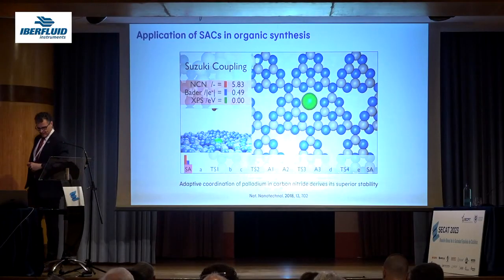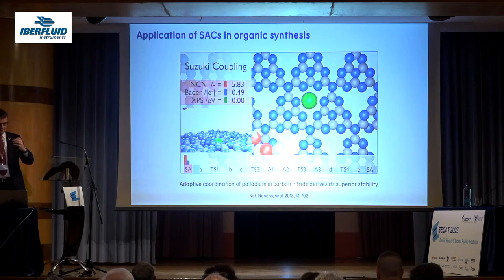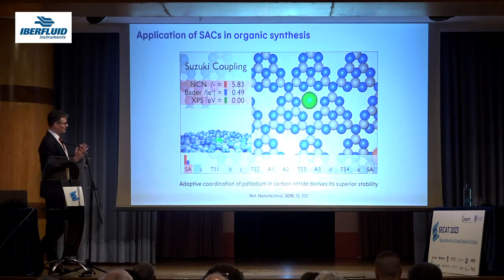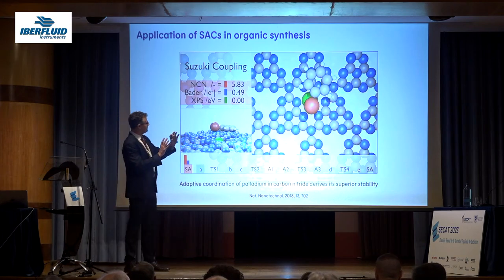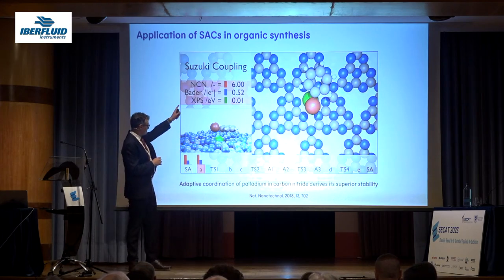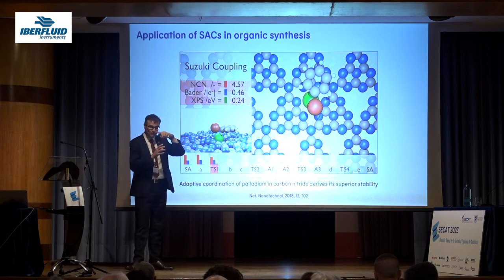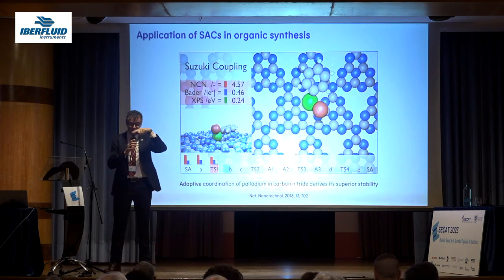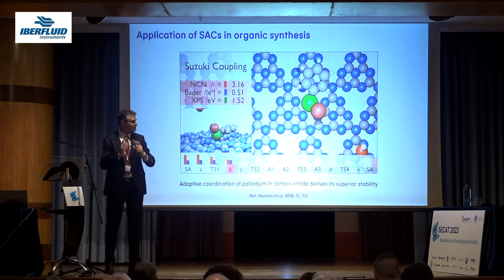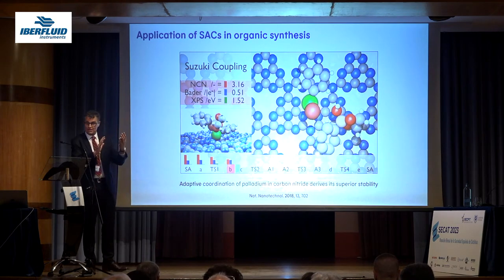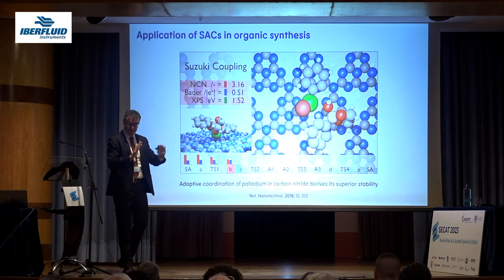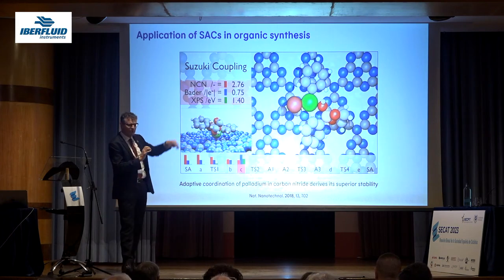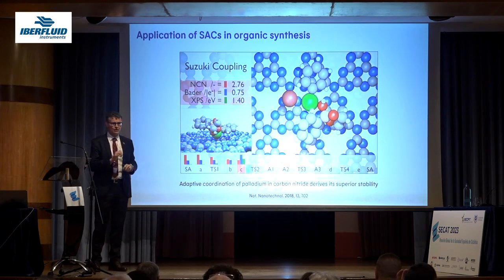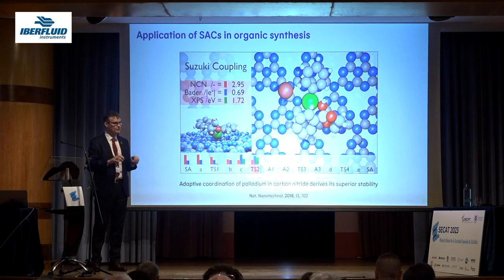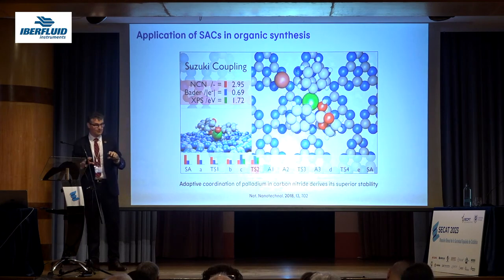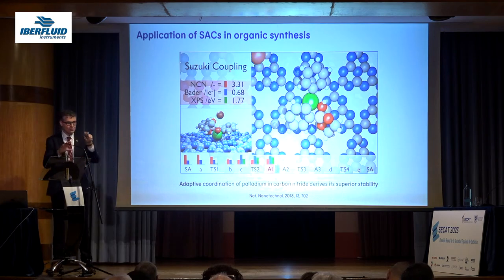And so we were investigating this further, how these cavities stabilizing these single atoms work, and we could see that this is the nitrogen, this is the coordination number, so to how many nitrogens around the cavity the palladium is connected to. Typically it is connected to around 6 nitrogen atoms in the cavity. And during reaction you can see that it loses coordination because it attaches the different reactants, intermediates, and so on, but it moves in the cavity.